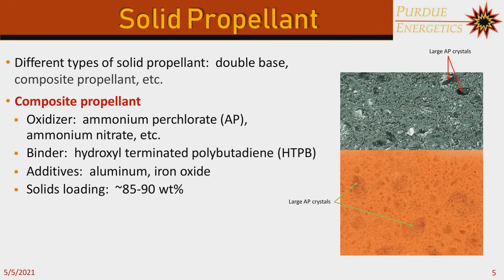The binder is typically a small percentage of your propellant, and the way it works is that first it starts off in a liquid state, but then with some heat, you can thermally cross-link that polymer, and then it cures into a solid state. And that is essentially what holds the propellant together. So first, when you're mixing the particles together with the binder, it starts off in a slurry state. I like to think of that as the consistency of wet sand, for example, and then you pour that slurry into a predetermined mold, and after you thermally cross-link it, it cures into a solid state, and I like to think of that consistency like an eraser, essentially.